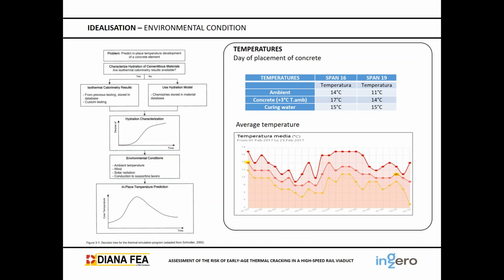Related to the idealization, okay, the environmental conditions, we take the average temperature of the month in which the concrete was poured, and we have two spans in which we have measurements, and there were lab tests of the concrete resistance, so we decided to study those two spans, which were the 16th and the 19th. The ambient temperature was 14 degrees or 11 degrees. The concrete was poured at 3 degrees plus the ambient temperature, which were 17 and 14 degrees. And the curing water was supplied at a constant temperature of 15 degrees. Okay, so we have the temperatures of the process.